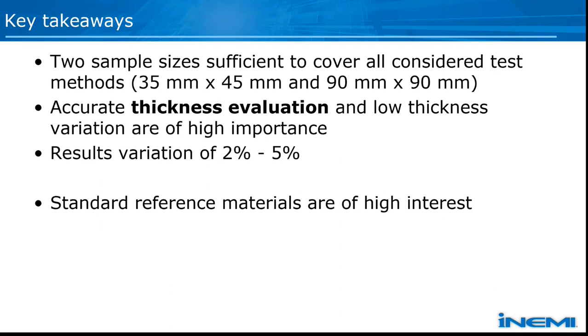With that in mind, we were seeing results variations in real samples on the order of plus or minus 2% to plus or minus 5%. Most of those, unless it was something anisotropic, are right around plus or minus 2%. Some even did better than that. But particularly when you start including anisotropy, some had potentially unexpected anisotropy, and we did get into those higher numbers. A lot of those also were materials that had some interesting variations in the thickness measurements themselves.